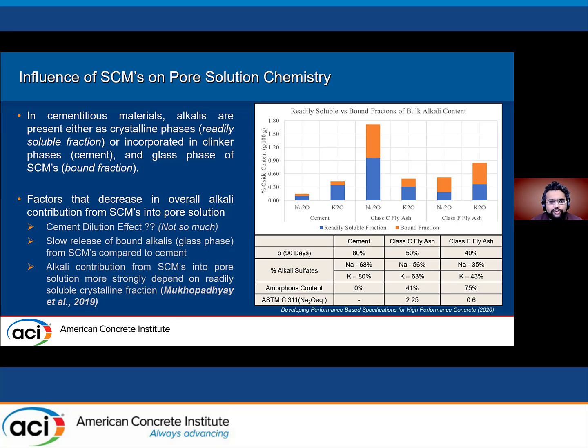And second is the slow release of bound alkalis. When we measured the alkali sulfates, or the crystalline fractions that are readily available, the table on the right shows it's an average of 75% for cement, but for class F fly ash, it's around 38 to 40%. So that means 60% of the total alkalis are released during the entire life of hydration. And if you see the degree of hydration that we measured at 90 days, for cement approximately 80% was hydrated, but for class C fly ash, only 50% hydrated. And for class F, it was even lower, around 40%.